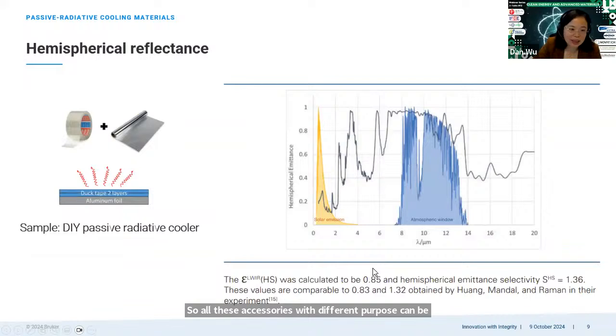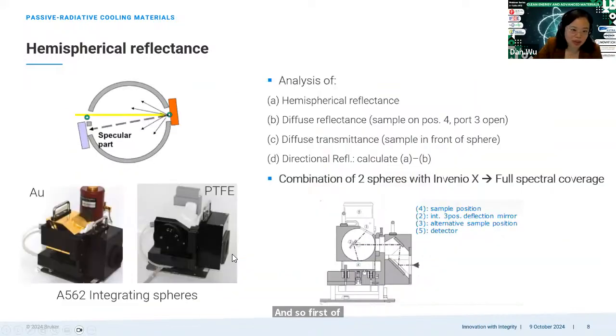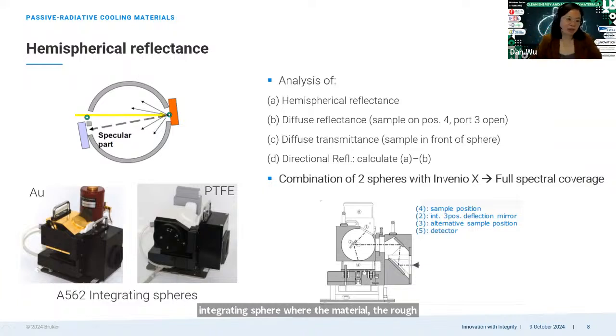And so first of all, let me shortly introduce the integrating sphere, where the rough surface material is measured. As my colleague Matthias Kessler has introduced, with a rough surface you will have light introduced from one direction, but scattered in many directions at the end. So with such an integrating sphere, you are able to collect all the light from all the directions. In this case, you can analyze the hemispherical reflectance, the diffuse reflectance, or diffuse transmittance if you put the sample into the beam path and let the light go through the sample. And also you can calculate the directional reflectance at the end by subtraction of the different parts of the reflectance.